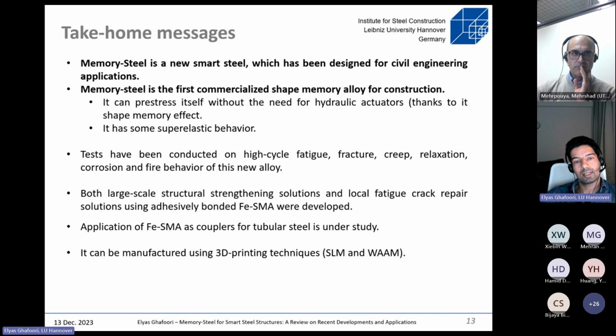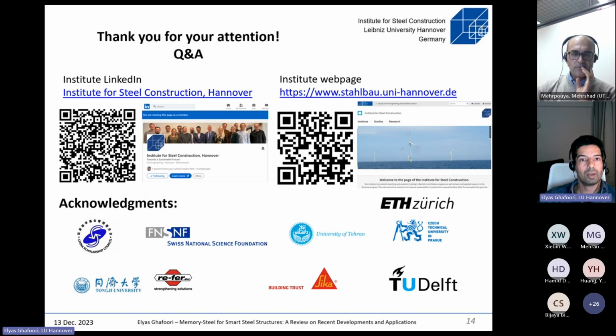And here, this alloy is not very much sensitive to a bit of more or less manganese or chrome. So it has a good stability for 3D printing application. So it's not very sensitive to the exact components and ingredients.